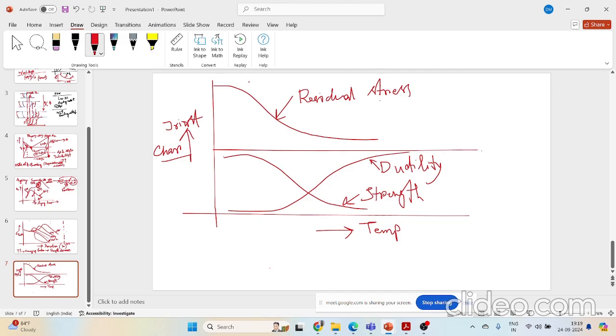The zone which will be close to your fusion boundary or weld nugget will be experiencing higher temperature, as simple as that. That will be experiencing higher temperature for longer time, and that will cause more severe reversion and grain growth, right? And as you go away from this fusion boundary in the heat affected zone, both the peak temperature and the high temperature retention period will decrease, and that causes lesser and lesser reversion and grain growth, which leads to gradually increasing hardness of the heat affected zone as you go away from your fusion boundary, right?